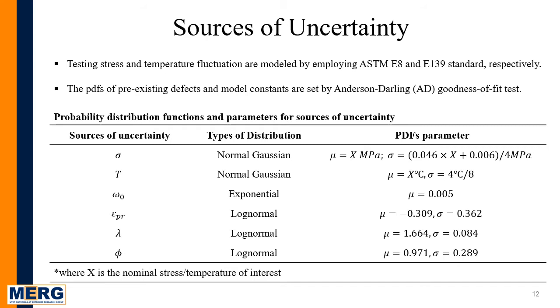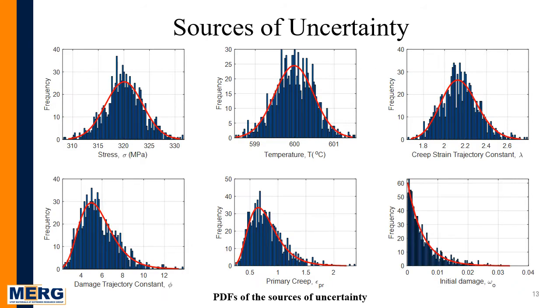In this study, testing stress and temperature fluctuations are modeled by employing ASTM E8 and ASTM E139 standards. And the PDFs of the pre-existing defects and model constants are set by the Anderson-Darling goodness of fit test. Now in this table, the sources of uncertainties are listed where stress and temperature are modeled by the normal Gaussian distribution. The uncertainty of initial damage is modeled by exponential distribution, and other model constants are modeled by log normal distribution. And these are the distribution plots for each of the sources of uncertainties. These plots are shown for a particular case of 320 megapascal and 600 degrees centigrade.